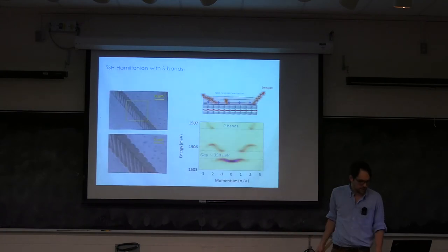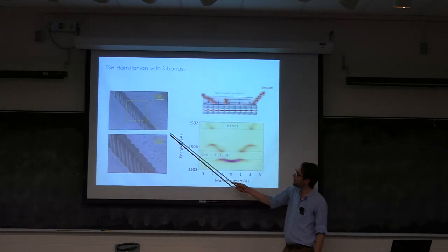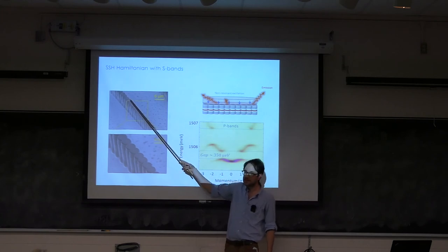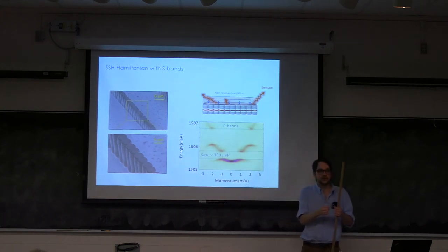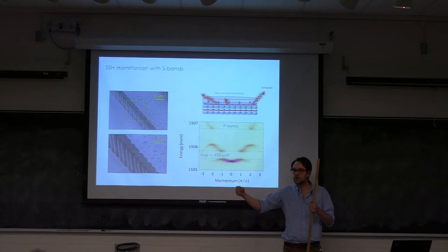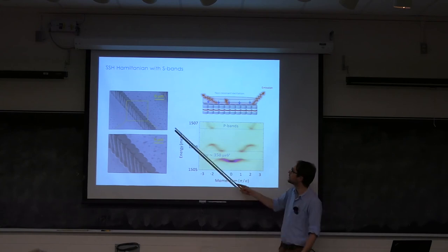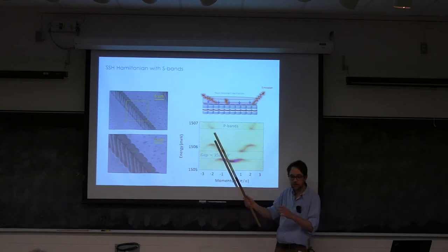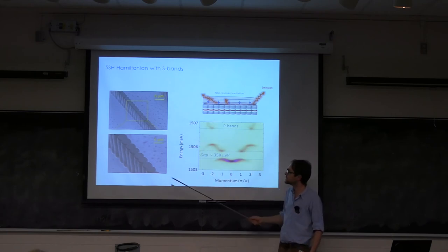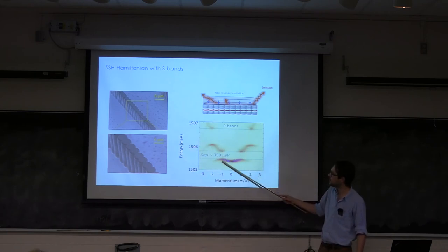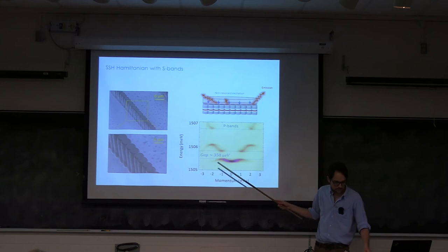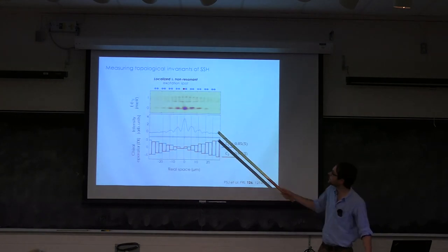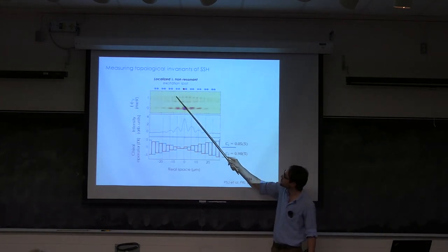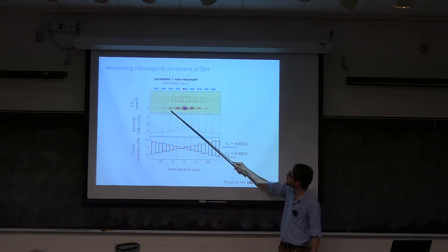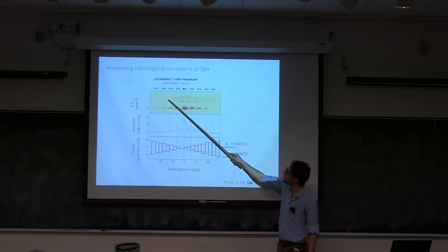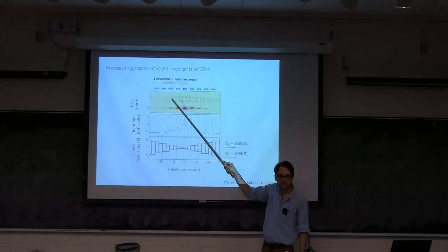All right, so we have done this. So this is again another lattice where, instead of having a zigzag, we have pillars that are close, far, close, far, close, far from each other. So we're going to work with the S band of the ground state of each pillar, the hybridization. And you see that you indeed have again these two bands that are separated. And what we do now is that we have a localized excitation. So these are the two bands in real space. So we have a bonding band, anti-bonding band, and this is the intensity profile.